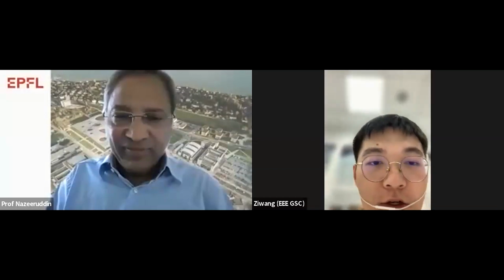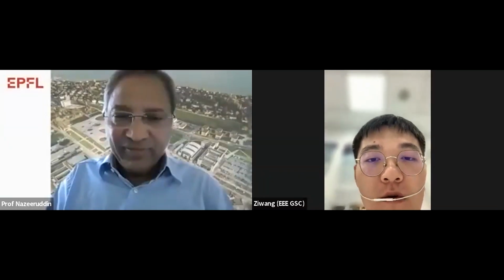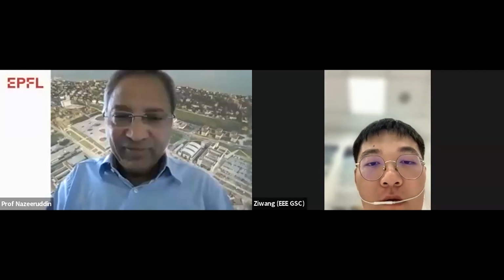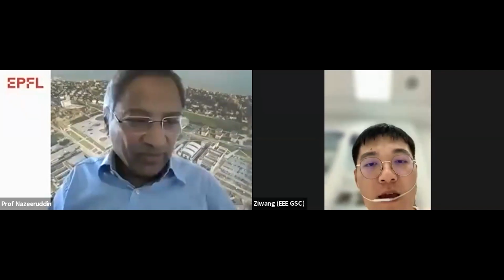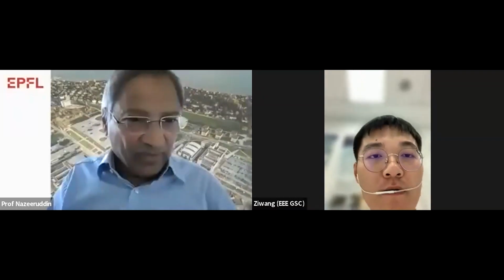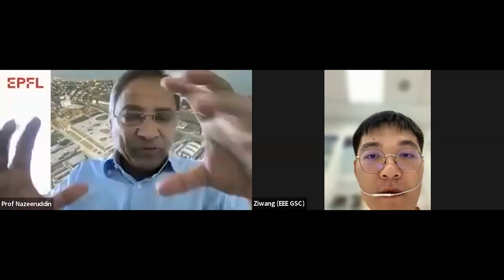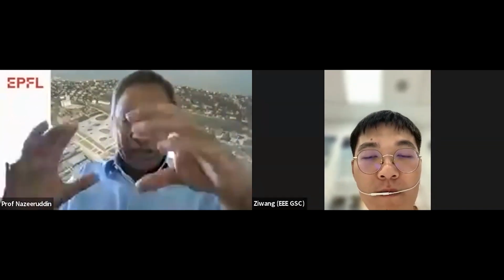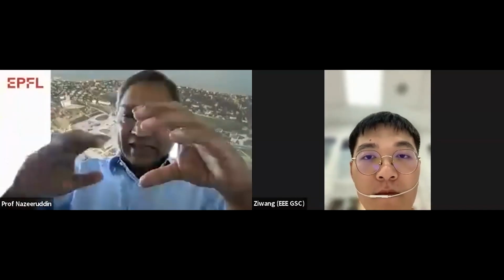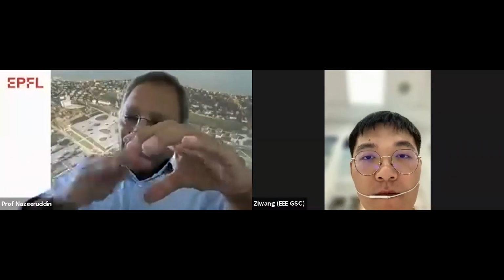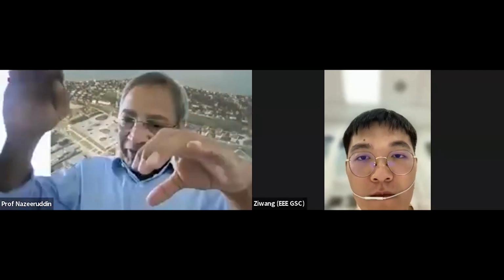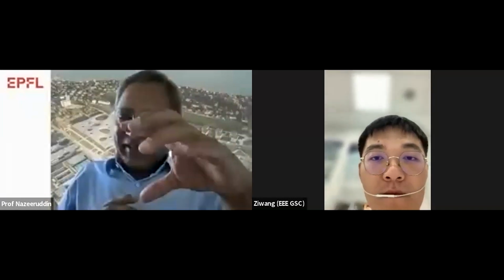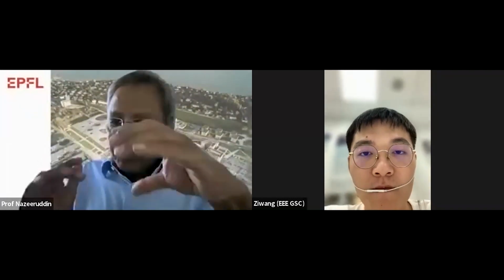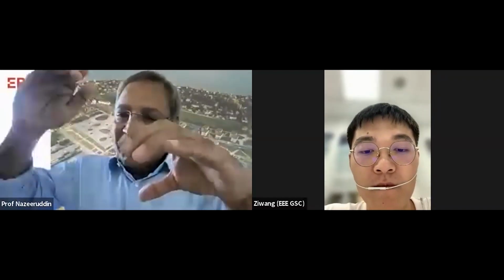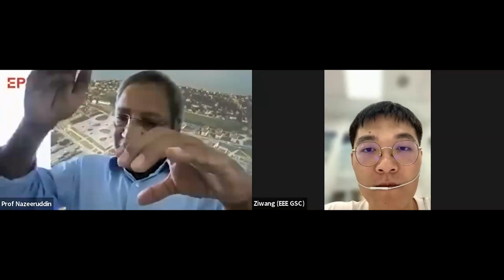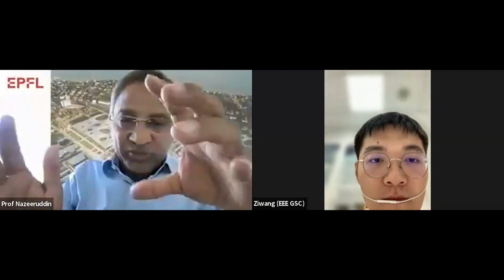Okay. Yeah, thank you. And next question is, when preparing a perovskite, will all the methods, including solution, two steps, vacuum deposition, and two step plus sublimation, give the same perovskite? Which method is preferred? Okay, so this is again subject to, for example, if you are working on a tandem solar cell, silicon perovskite tandem solar cells. Silicon has a lot of pyramids. Solution processing will not give us a uniform coating of the perovskite on the top of the pyramid and the valley. So if I select the pyramidal structure of the silicon heterojunction solar cell, then maybe we have to use a sublimation technique so that you can uniformly coat on the valley as well as on the peak. This technique is suitable for sublimation.